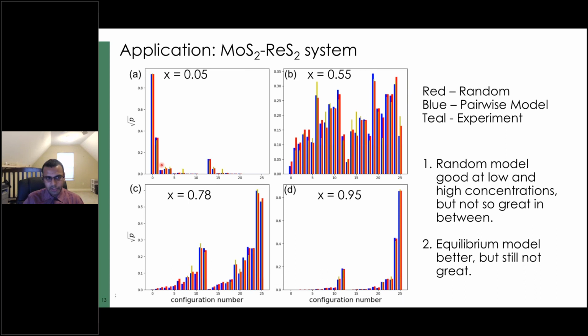And unfortunately, what this experiment is showing us is that a lot of the data that we're seeing can more or less be explained by random interactions. So certainly at low concentrations and at high concentrations, you see that the red columns are very closely matched to the teal columns. So that means that, at least if we just looked at these particular compositions, it would suggest that there's not really a lot of information to be had from these images in terms of trying to extract a particular interaction energy between either the pairwise or the triplet model.